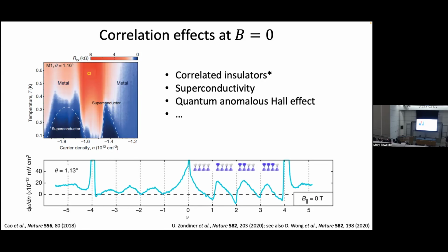And instead you get this sort of characteristic sawtooth pattern, which may have to do with sloshing of charge around in terms of different bands or different portions of the bands. That's still somewhat in question, but I would put an asterisk here that just seeing a resistance peak is not enough to say that it's an insulator. And again, every sample is a little bit different. There are other cases where you have quantum anomalous Hall effect from hBN alignment, so there's quite a bit of variability here.